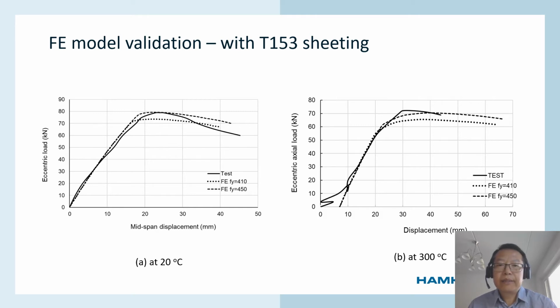These are load displacement curves for trapezoidal sheeting cases. Left is the normal temperature and right is 300 degrees. At the time of simulation, we only knew that the steel column has a grade of S355. Therefore, 2 yield strengths were used in the simulation, 410 and 450 megapascal. Those are typical values for S355. The actual measured yield strength is 460 megapascal in the flange in the later tensile coupon test.